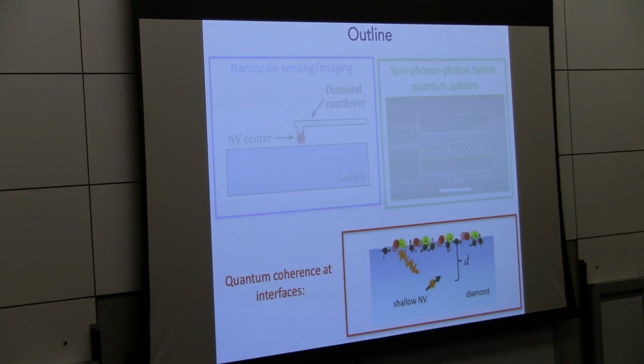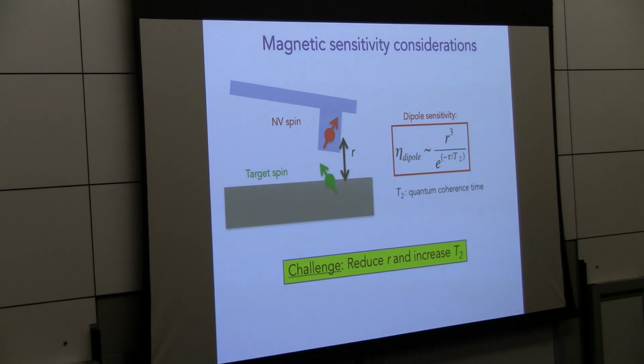Okay, so that's some work that we've done with imaging. Let me take a slight turn here to talk about this issue of quantum coherence at interfaces. We're particularly interested in this because if we really want to reach this regime of nanoscale or even sub-nanoscale spatial resolution, we need to bring our NV center very close to a sample. Let's say it's a target spin, a nuclear spin that we want to image. Our dipole sensitivity, the minimum number of dipoles we can detect in a 1 second measurement, is going to go as r cubed over e to the minus tau over T2, where T2 is the quantum coherence time. So we want really small separation and really long T2.